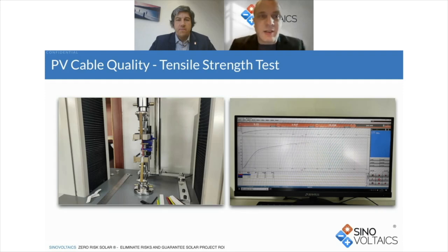Another important test where our team also sometimes comes across failures is the tensile strength test, which is conducted on the insulation and jacket, respectively. This test is to ascertain the compliance to the corresponding maximum stress thresholds. Basically, with this test, we measure the maximum stress a cable or cable material can withstand before it fails, for example, stress it is exposed to during installation or its operational life. Tensile strength is indicated normally in Newton per square millimeter or megapascals, and breaking elongation, they vary for different materials.